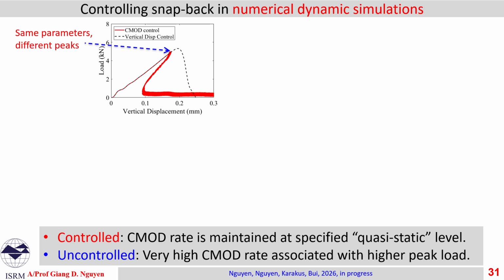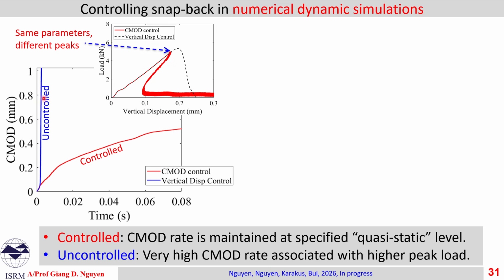We also observe a difference in the peak load. The same parameters are used, but different types of control lead to different peak loads. The explanation is the rate inside the fracture process. For the uncontrollable one, beyond a certain moment, the crack mouth opening displacement jumps very sharply, indicating a very high dynamic effect due to fracture and release of energy. The controllable one is very mild.